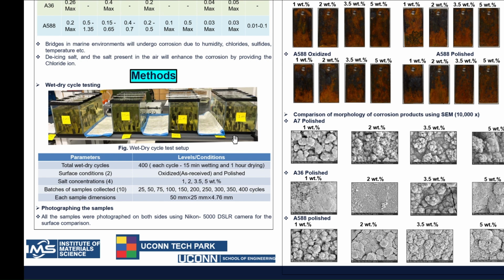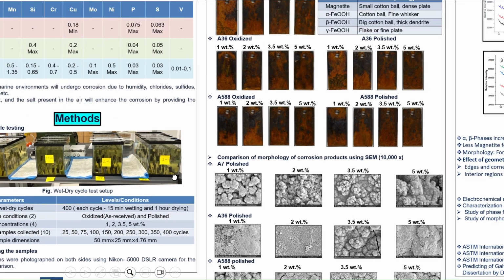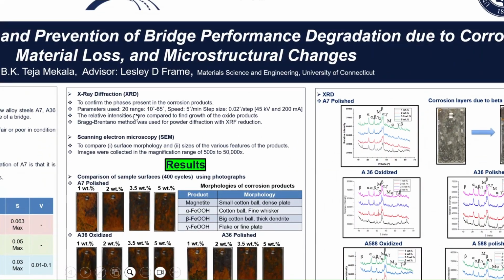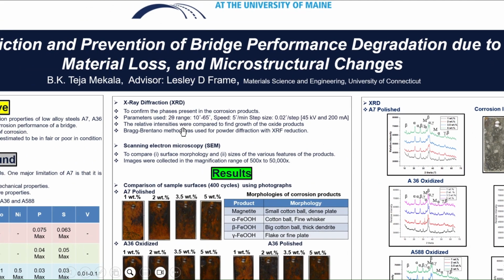In the wet dry cycle testing, each wetting time in the cycle is 15 minutes and drying is for 1 hour, and 400 such cycles were performed. Batches of samples were collected at different time points as shown in the table, and each sample's dimensions were 50 mm, 25 mm, 4.76 mm. The samples collected were photographed using a Nikon 5000 DSLR camera for surface comparison. Once the samples were collected, X-ray diffraction was performed to confirm the phases present in the corrosion